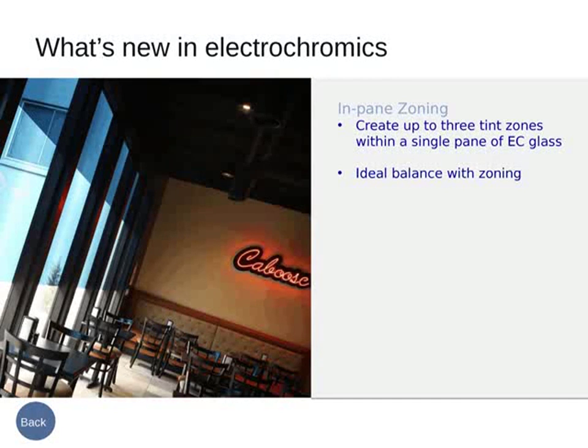To go from the completely clear state to start noticing a tint takes probably 2 to 3 minutes, and then you'll see a noticeable difference. It's preferable not to have an instantaneous effect, but rather a real gradual tint, because we don't want the end user to have a jarring experience. I always use the example of leaving a movie theater and going out to the bright sun. It's an immediate switch from dark to clear. The idea is that it happens gradually without really being noticed unless you're cognizant of it. And like I said, in about 2 to 3 minutes, you'll begin to see a tint.